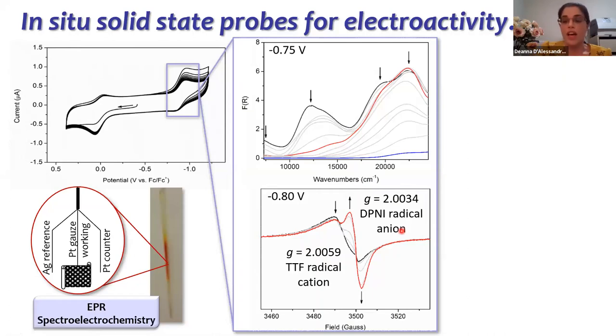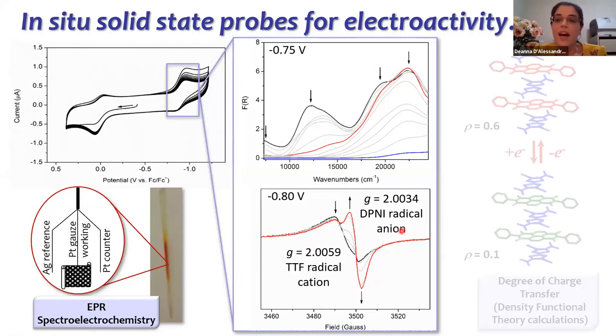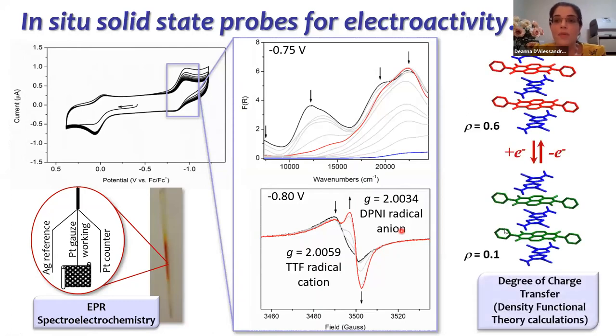So what we see here is that in the as synthesized state, we already have a certain degree of charge transfer, which we can actually model using some computational chemistry, showing that we already have the TTF in its radical cation state, the naphthalene diimide in its radical anion state.